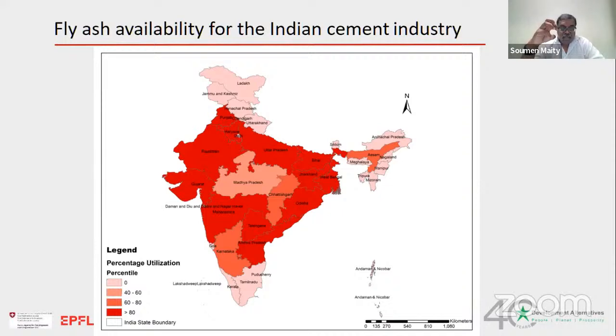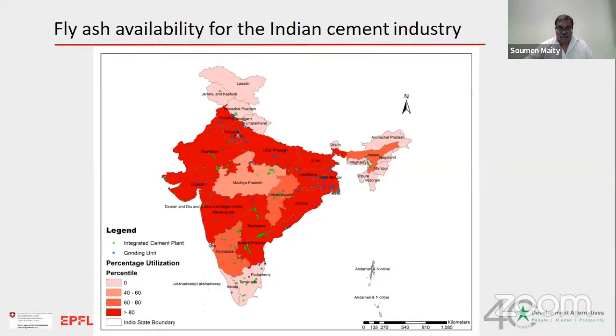Now, if this is the kind of availability of fly ash scenario, let me plot the cement plants on top of this. The blue dots that you see are grinding units, and the green dots are integrated cement plants. So still, if you see in Madhya Pradesh, the central part, in that area there is fly ash available. So it makes much more sense to look at PPC-based cements.